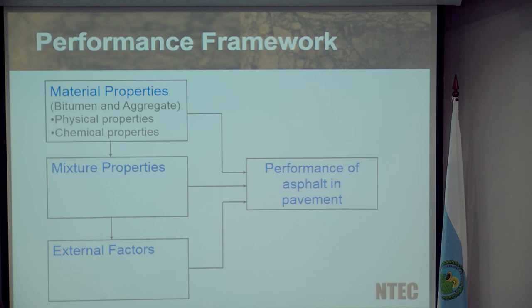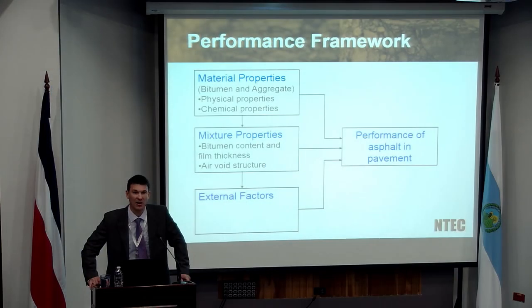The mixture properties, well, effectively the two main drivers are binder content. And obviously the binder's role is to cover and to coat the aggregate in an asphalt mixture. Increasing the amount of that particular binder obviously will improve the situation. But also looking at the air void distribution or the air void profile of materials to see how we can either limit water getting into our materials by making them relatively dense, or if water does get into that material, how can we connect the void structure so that the water doesn't remain in that particular material.